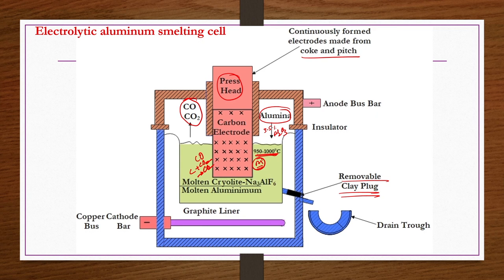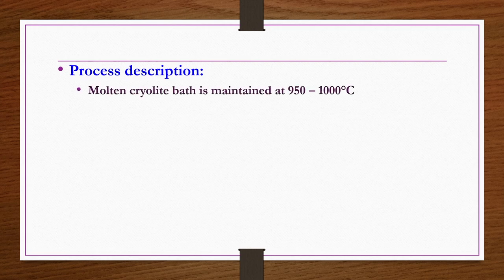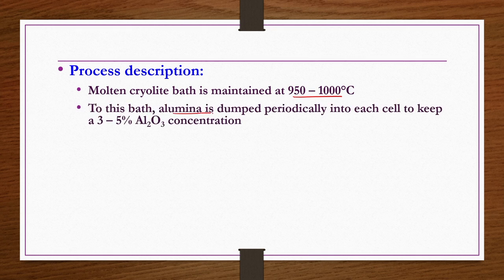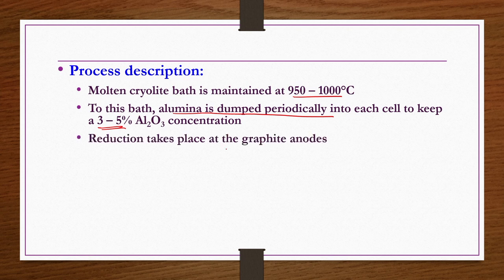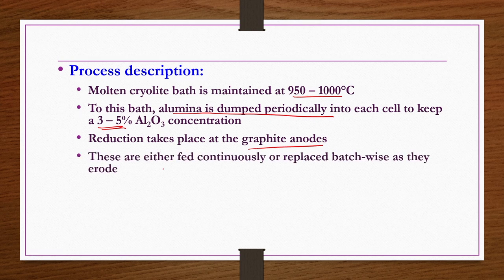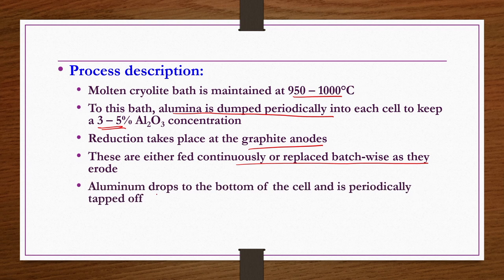So, as the electrodes are being consumed for this reaction, they are continuously formed, and then supplied continuously into the cryolite bath, okay? So, the description of this process: molten cryolite bath is maintained at 950 to 1000 degrees centigrade. To this bath, alumina is dumped periodically into each cell to keep 3 to 5% alumina concentration within the bath continuously. Okay? Reduction takes place at the graphite anodes. These are either fed continuously or replaced batch wise as they erode, because the reactions are taking place at the graphite anodes. Okay? Aluminum drops to the bottom of the cell and is periodically tapped off.